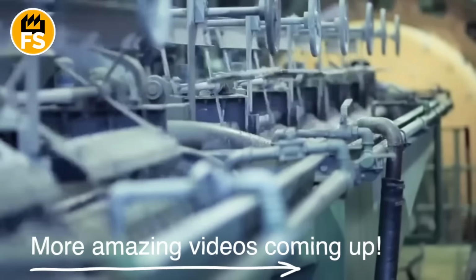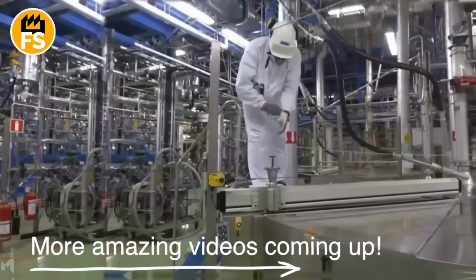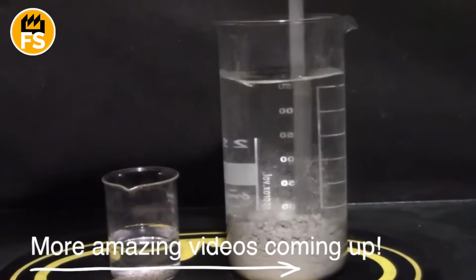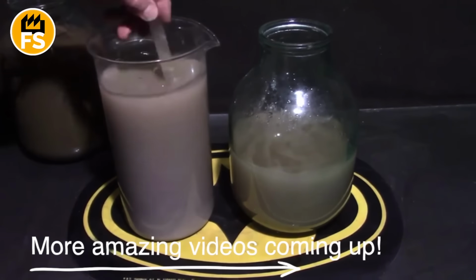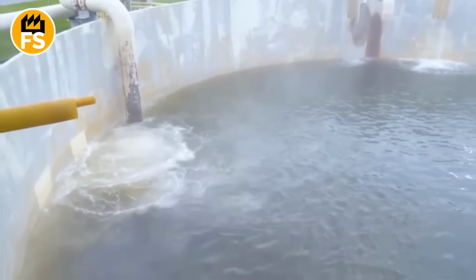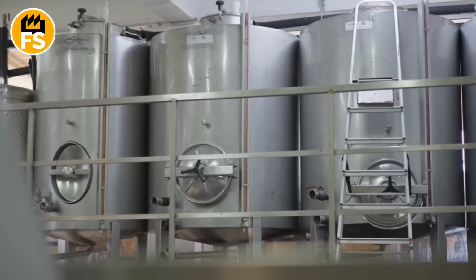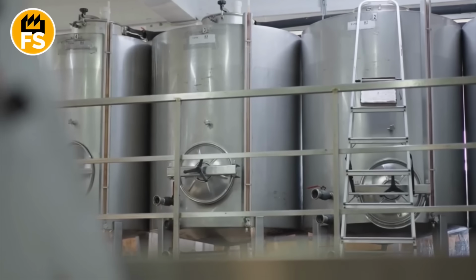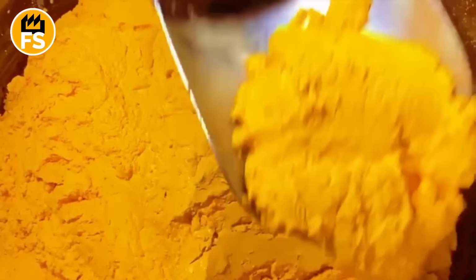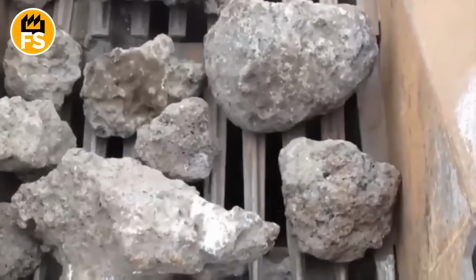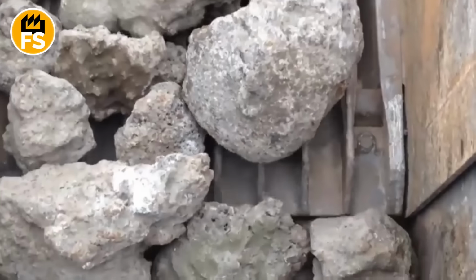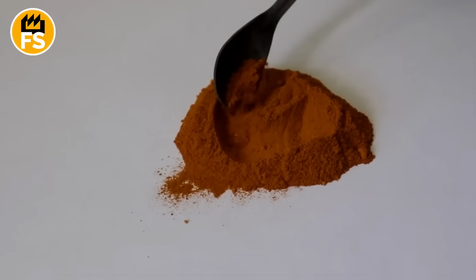It's filtered, removing insoluble impurities, followed by precipitation, adding reagents that selectively bind vanadium. Inside the reaction vessels, a fine precipitate appears, gradually compacting and separating from the liquid. After washing and drying, this material becomes vanadium pentoxide, a bright powdery substance with a distinctive yellow-orange hue. From this moment on, vanadium stops being a hidden component in slag and becomes an independent industrial raw material.